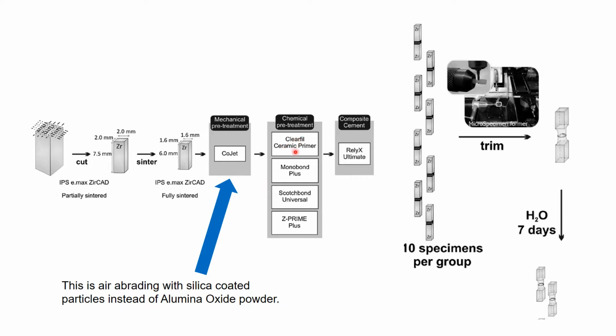So the Clearfil Ceramic Primer, which is once again a dual monomer primer. Monobond Plus is a dual monomer primer. Scotchbond Universal does have silane and MDP in it as well, and then there's Z Prime Plus. I'm not sure of the ingredients of this. It may just be MDP. I don't know if there's silane in this. Then they used a single cement for all of them, RelyX Ultimate. And they stored the specimens for 7 days, and they did what's called a microtensile test, which is the most accurate way to do bond testing.